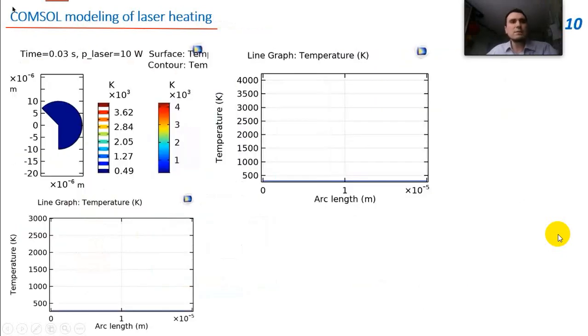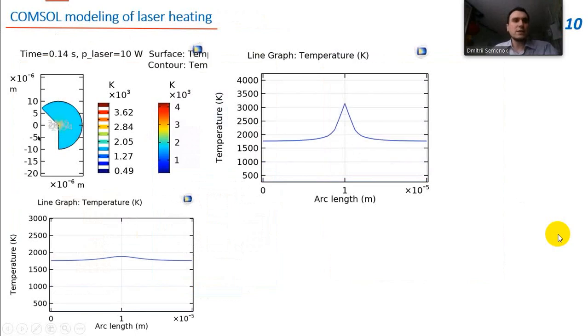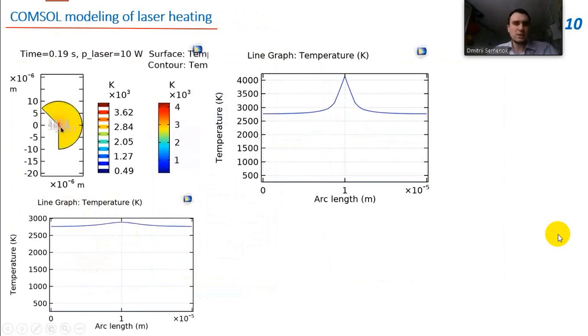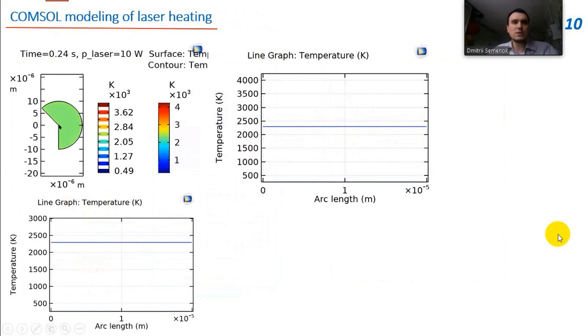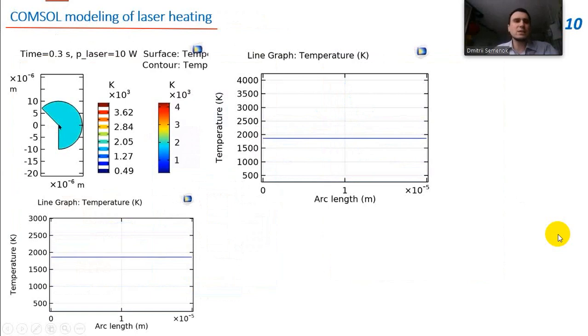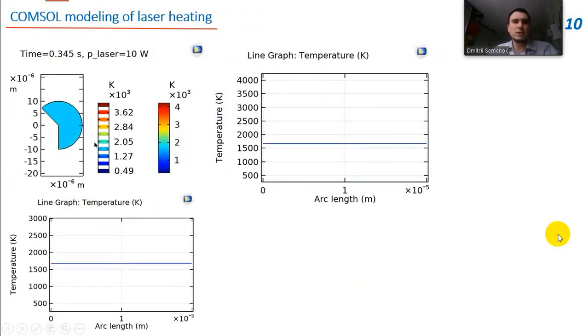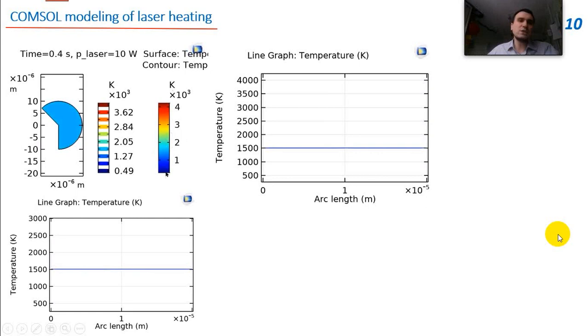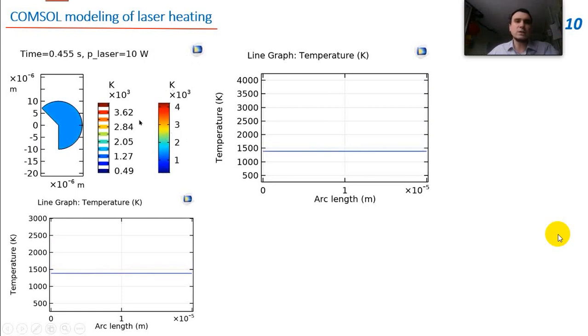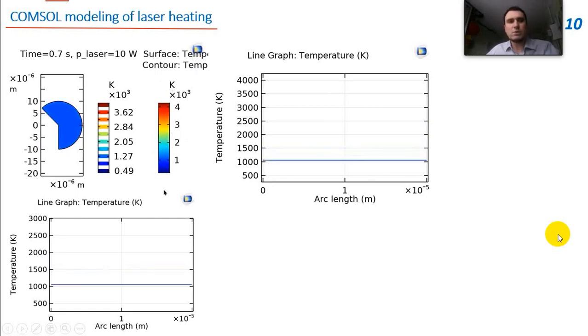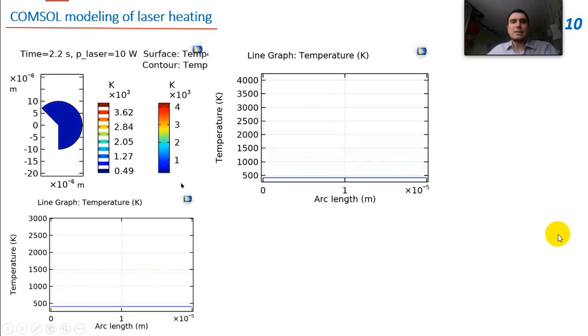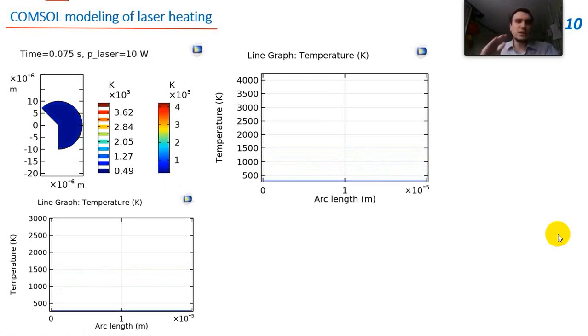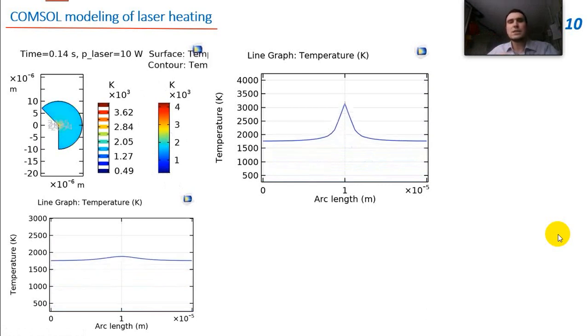We even did some COMSOL modeling of this process of laser heating, and you can see how the temperature rises during the laser pulse. It's from milliseconds to seconds pulse. The temperature can reach even 4,000 kelvins. The main problem during the heating is that the diamond itself has very high thermal conductivity, and if the metallic sample is connected with that diamond, it cannot be heated.